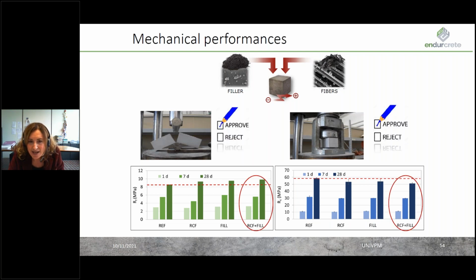The experimental results have shown that the joint use of these low-cost fillers and fibers does not significantly affect the mechanical performances of concretes. Next.